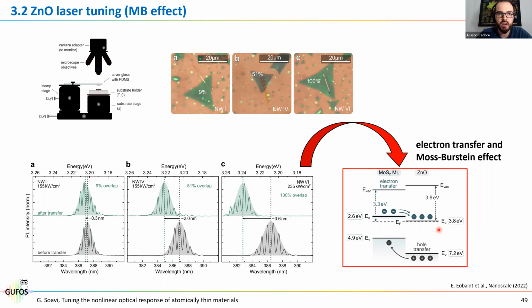I guess you're always shining light directly on the nanowire, right? So let's say this 51%. So if you measure outside the MoS2, you don't see anything, or you see? No, so actually that's also quite tricky. So that's also one of the reasons you need to pump very hard.